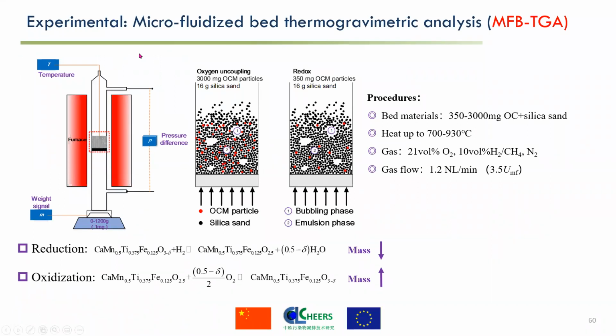Then we use the micro fluidized bed thermogravimetric analyzer (MFB-TGA) to study the multiple cycles and the kinetics of CMTF. The core of MFB-TGA is the bubbling bed reaction. We add 350 milligram CMTF particles into the reactor for the redox kinetics test, and 3 gram particles for the oxygen release test, and the other bed material is silica sand.